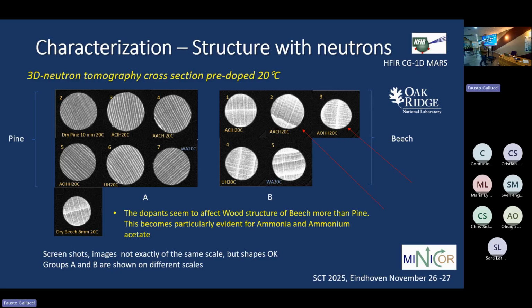And what is interesting here is also that when you dope, you see that beechwood is highly affected, whereas pine wood is not. That shows you a very good example of how important a role nature can play in our material. So that it has a high level of architecture in it, which is hard to reproduce by man as well. Okay.